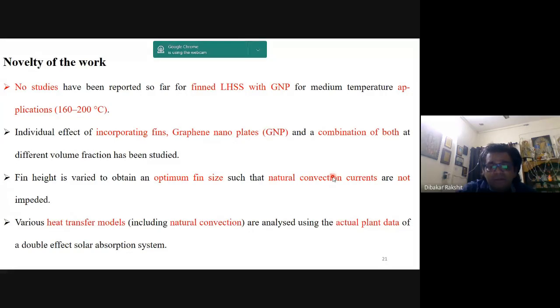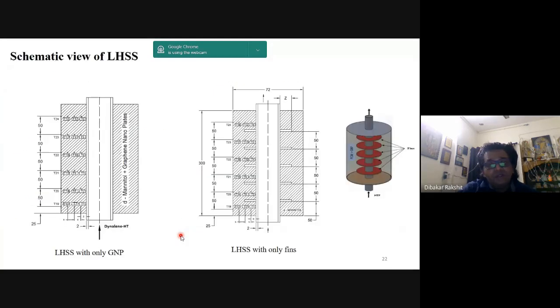And then we compared the various modes of heat transfer, the convective and the conductive modes, happening in the actual plant. Somehow we got data on one double effect solar absorption system which is somewhere in Europe. We tried to match it with our experimental results by scaling it down, and at the same time we tried to match the numerical analysis we have done with that as well. So that is shown over here.